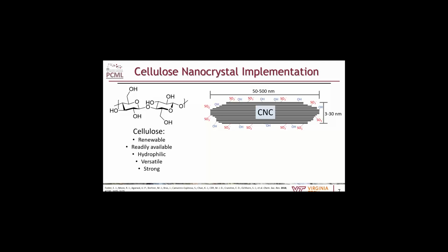But once you have these crystals isolated from your acid bath, you usually want to wash out that acid so you can actually use them, and then you have an aqueous suspension of CNCs. You can then dry these CNCs and have a nice powder that you can put into various polymer mixes and try to use that way. Long-term storage is pretty easy that way.